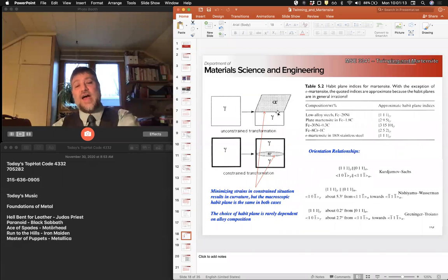Right? And so if we have an unconstrained transformation, we get a big kink. In a polycrystal where we have constraints, we get these lenticular shapes instead of big plates or slabs, because this is going to help maintain the shape and minimize the elastic distortion and the amount of plastic strain that has to be accommodated by the neighbors. Okay, so Martensite in all systems generally will form orientation relationships.